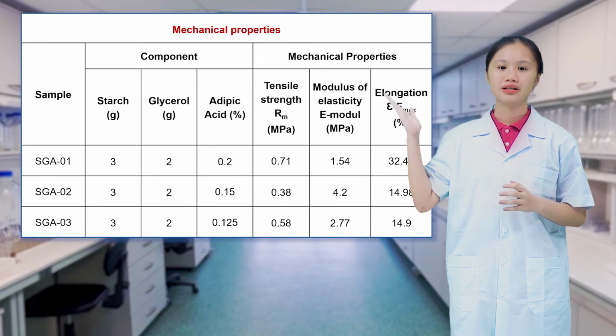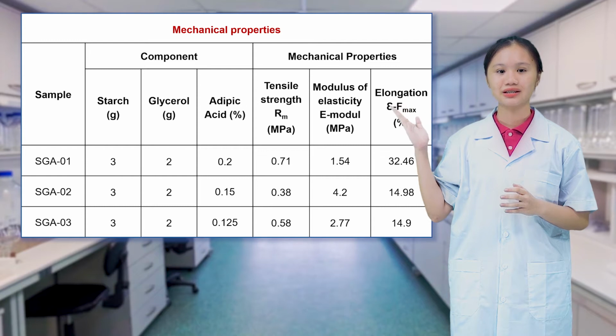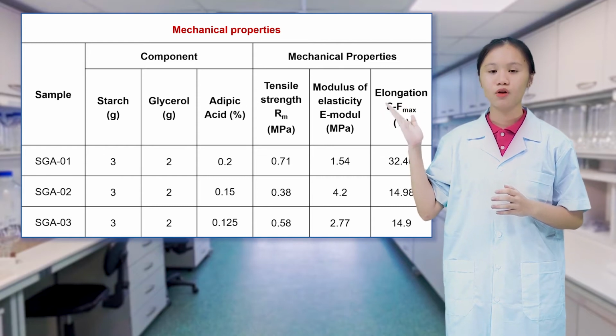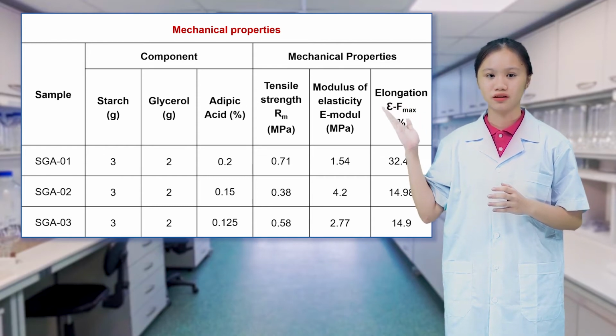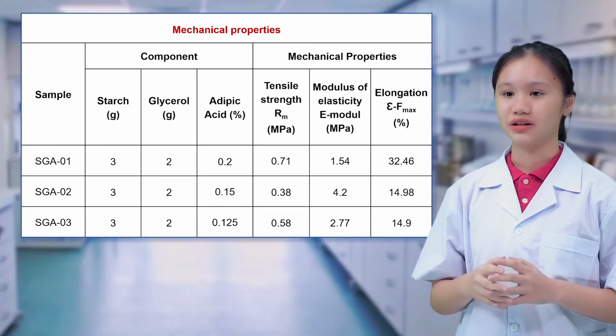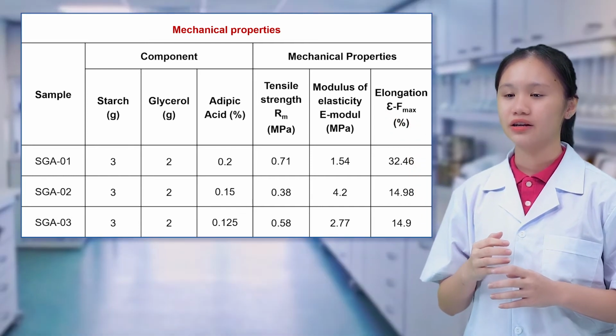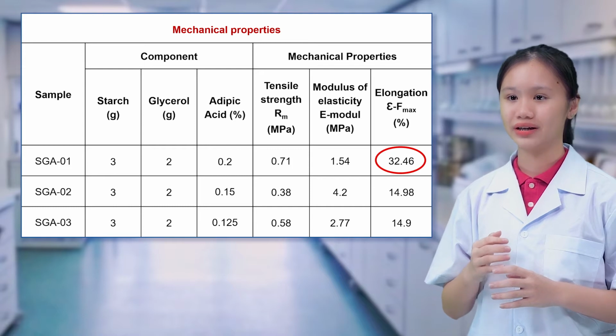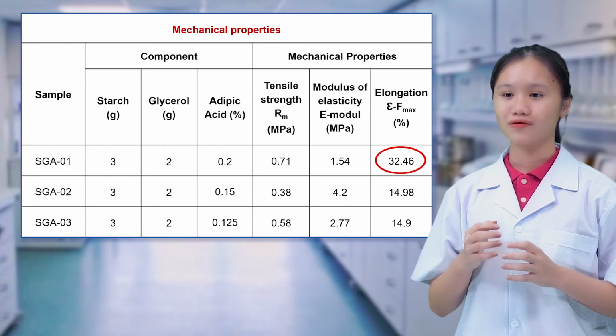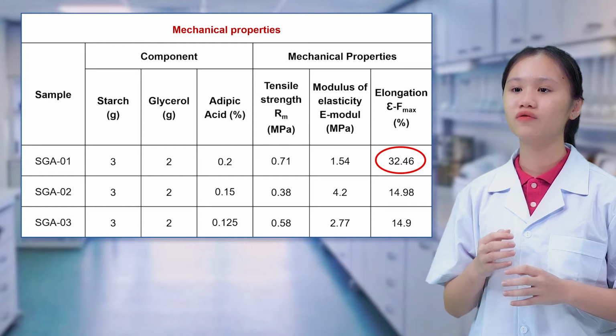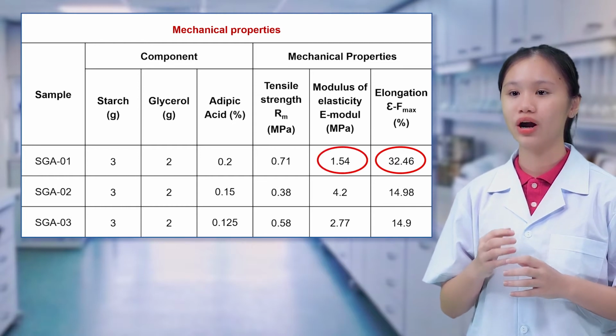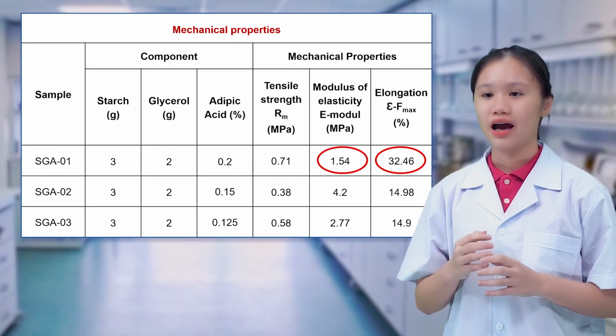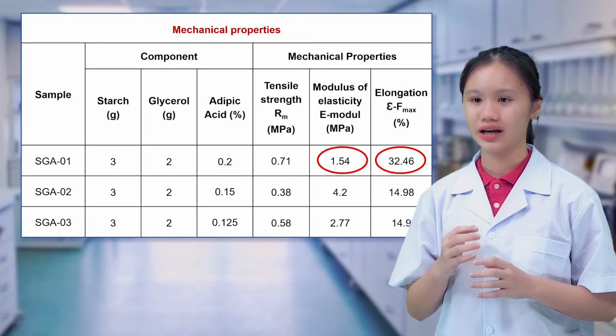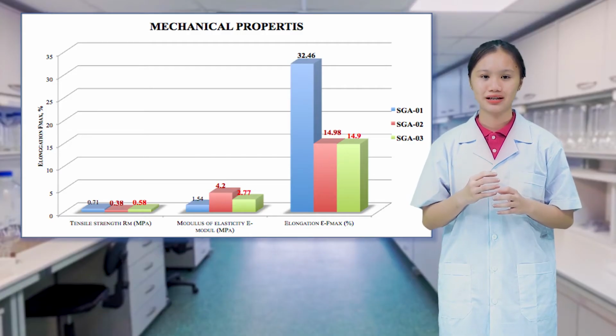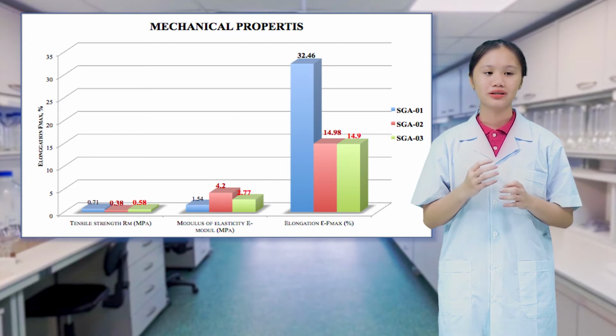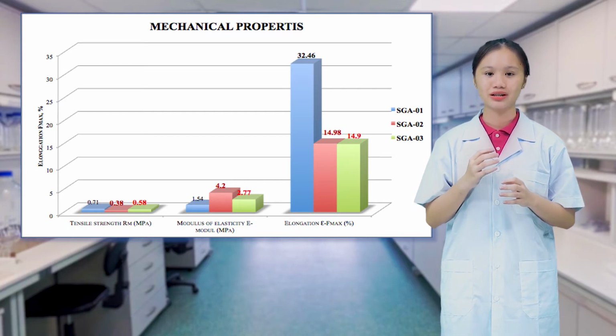The mechanical properties are used to determine the elongation and tensile strength of the film. Here, the sample SGA01 showed a greater tensile strength than the others, and its elongation at maximum force, Fmax, at nearly 32%, was also the greatest. Besides that, the E-modulus of SGA01 showed a lower value than the others, at 1.54 MPa. Based on the data, we can assume that the SGA01 sample with 0.2 adipic acid had good mechanical properties, while still supporting good elongation and impact resistance.